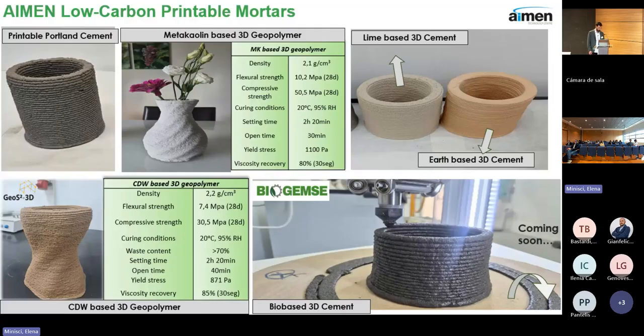In the bottom left, it's our first geopolymer. It's a construction and demolition waste-based 3D geopolymer that we developed in the framework of the Geo3D project. And in this material, the mechanical strength was quite good as well, 30 megapascal, more than enough for structural application, but I just want to highlight the waste content over 70%, which is a very good result to be in accordance with the circular economy.